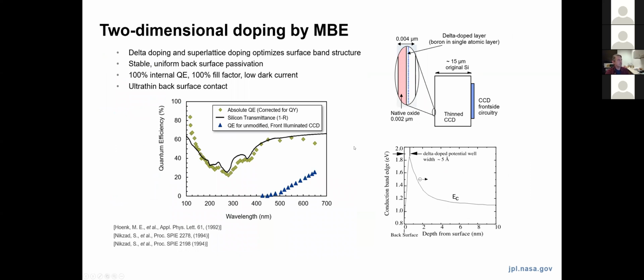So how do we do this? To get rid of the potential well that would naturally occur at the backside of a silicon sensor, we essentially introduce charge at the back of the detector. And that charge is introduced by growing a new silicon lattice that has a really high concentration of dopant atoms added to it. This counteracts the charge that would occur from those dangling bonds and bends the bands back in the direction that you want in order to promote the collection of charge carriers that are introduced right at the surface of the silicon. And so this is called delta doping, as originally conceived, because these dopant layers essentially appear as a delta function in the growth process that's used for this fabrication.